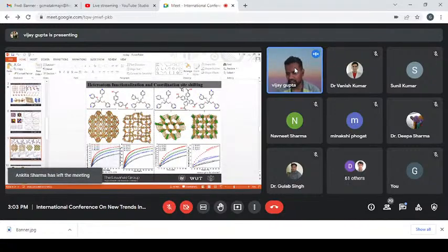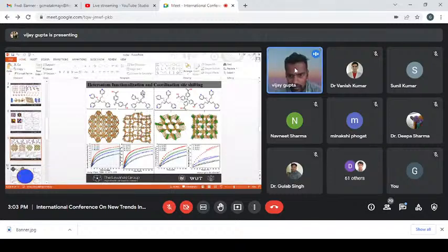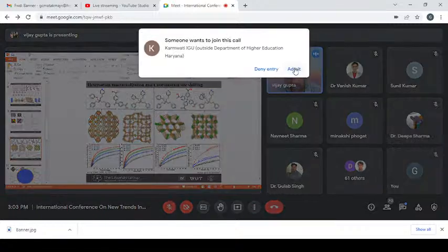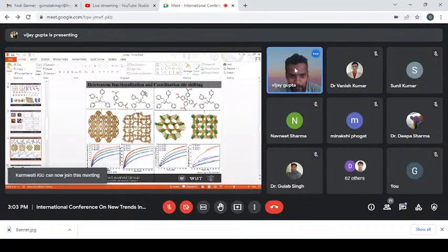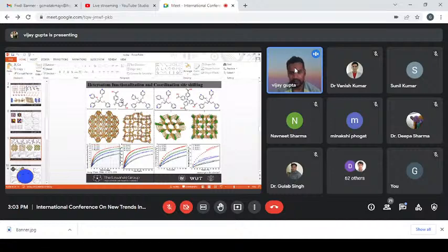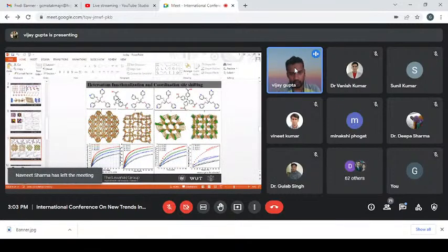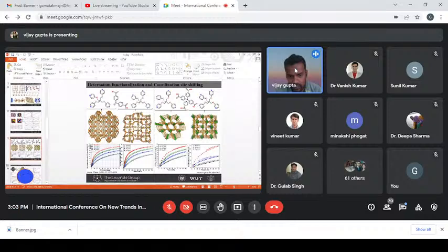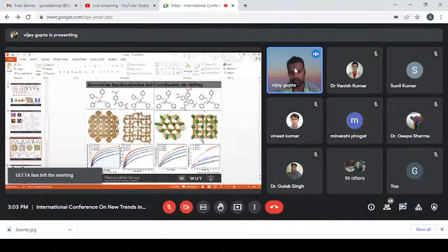The other thing is coordination site shifting. Here this is a 4-pyridyl, and this is 3-pyridyl. There is some problem in the slide, it should be 3-pyridyl. If we shift this coordination site, that will obviously result in a different architecture. So here you can see, using the same carboxylate and same metal, just changing the coordination site, we have two different frameworks, and you can see the adsorption profile of both. In this one, CO2 adsorption is much higher at different temperatures, but in the other one, CO2 adsorption is comparatively lower. And it happened in the other case also. So this is another strategy for how we can enhance the CO2 selectivity in the framework.